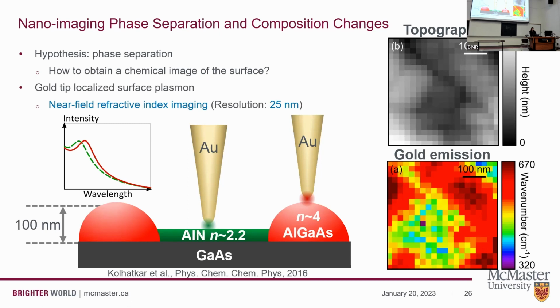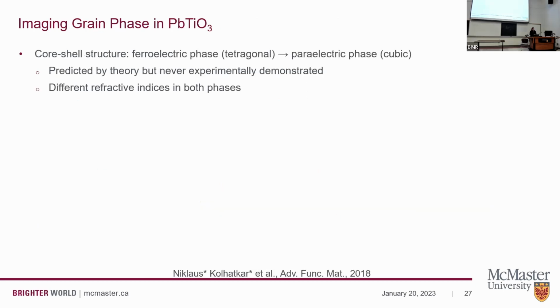So this shows us that we had a technique that could go beyond just imaging the chemical composition, but also look at composition changes and refractive index changes. Now we then wondered, between the different crystal phases in our ferroelectric material, should we expect a change in refractive index? The answer to that is yes. And we went back to our lead titanate nano islands.